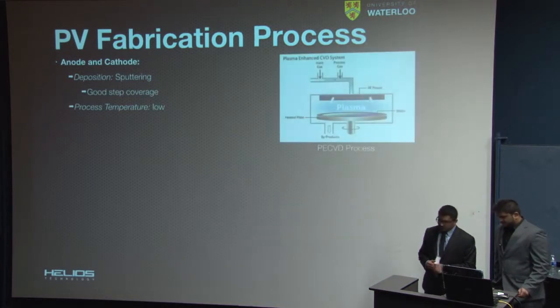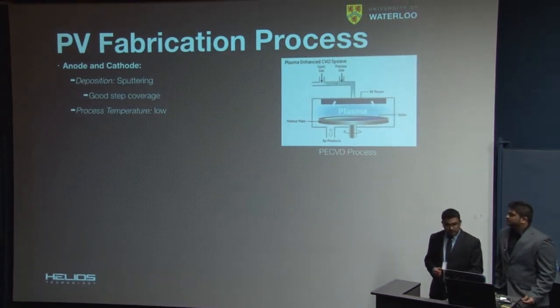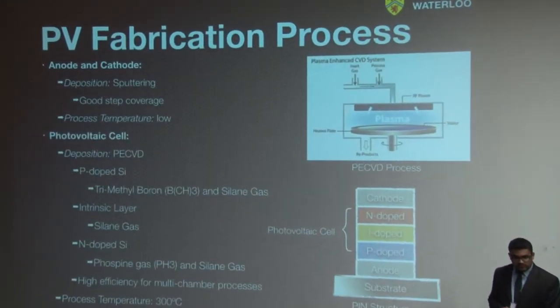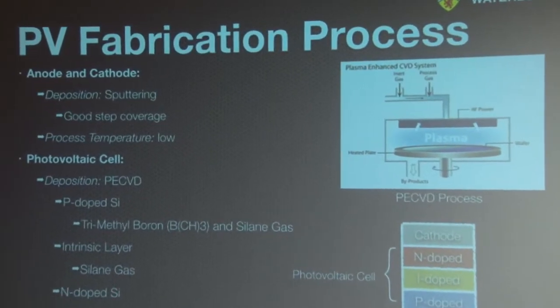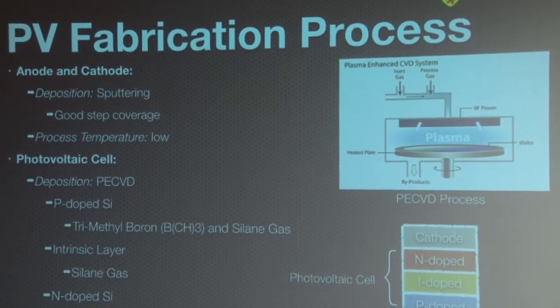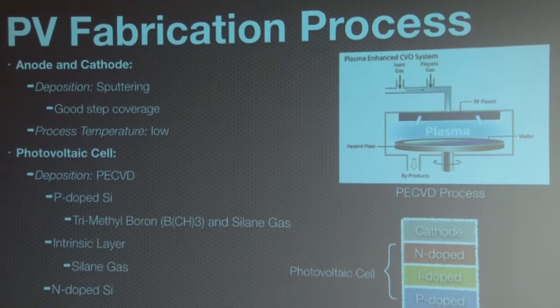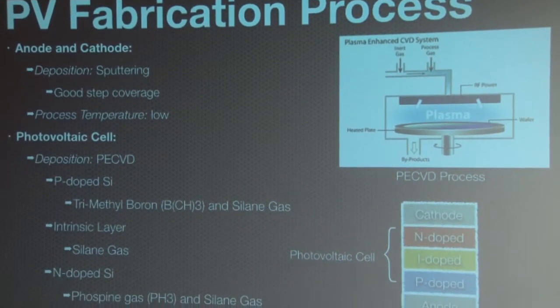So, our PV fabrication process: the anode and cathodes were done through sputtering, which is ideal for this because it provides us good step coverage, and it also allows us to use a low process temperature, which is ideal for some of the materials we're using.